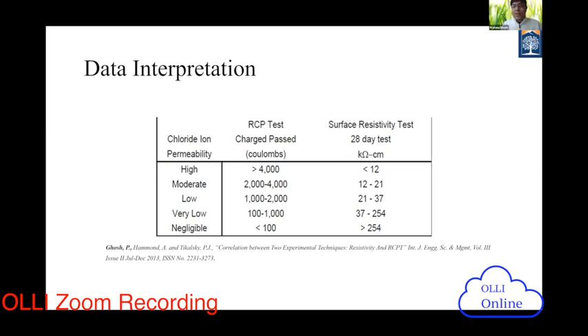Sometimes surface resistivity values are really high in the long term, at 28 and 56 days. So these are the advantages we are talking about. With the newest measurement technique and newest material, we are getting very low chloride ion permeability. Very low chloride ion permeability means very little diffusion. Again, we are coming back to the original talking point: basically, we have to get less diffusion and a big initiation time.